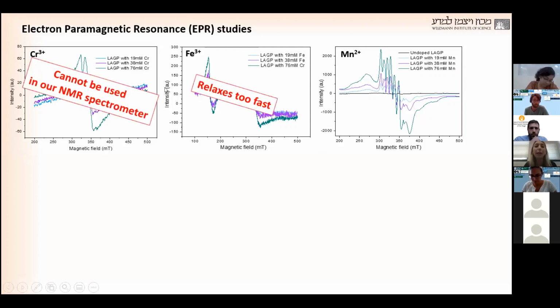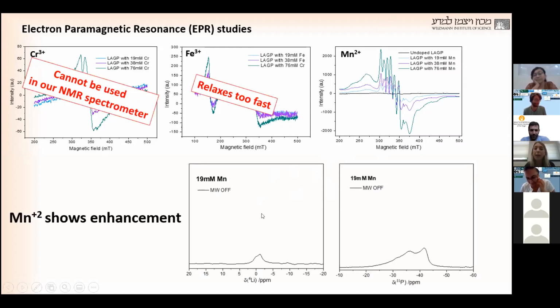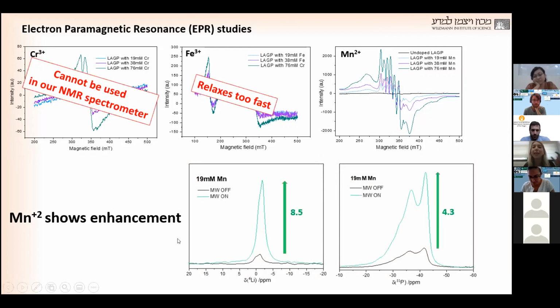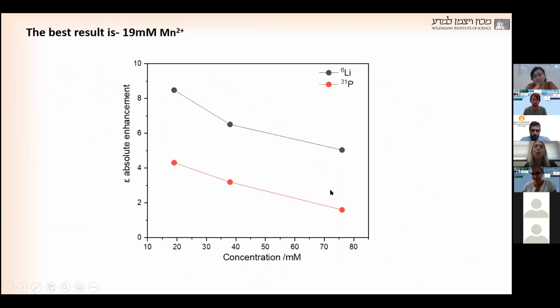We wanted to use chromium and iron because they looked promising, but we found out that we cannot use them, because we have difficult techniques, so we use the manganese. And when we did the NMR, we can see the spectrum of lithium 6 and phosphorus 31 isotopes. And when we radiate the microwave to create this polarization transfer, we can see that we have enhancement of the signal with good factors, so we can use this manganese for our purpose. It's also important to see which one of the concentrations, the 19, the 38, or 76, is the best one to use for this enhancement. And we found out that the best one is 19 millimolar manganese.